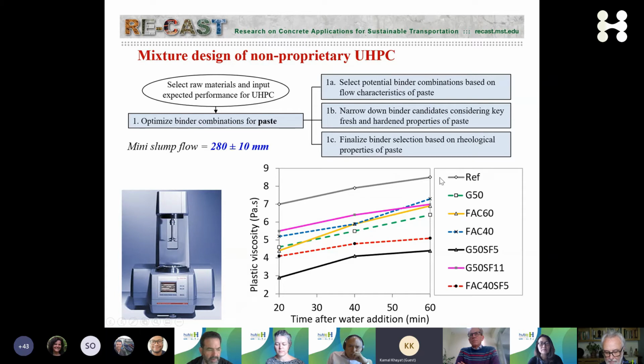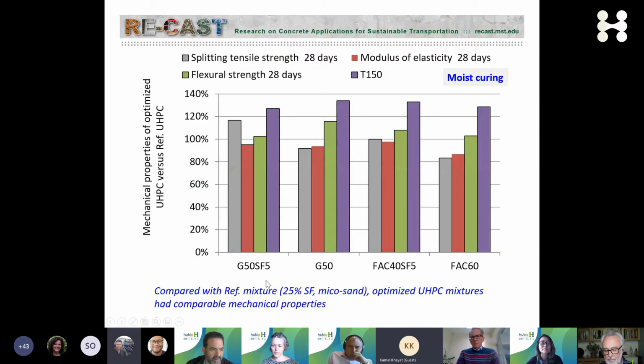We could see here some of the proprietary mixtures, like the one that was used in Sherbrooke, with 22 to 25% silica fume, is highly viscous. And by using different supplementary cementitious materials, fly ash, slag, silica fume, and combinations, we can reduce the viscosity. That means the material can be a lot easier to work with. We've also replaced some of the very fine sand, quartz sands, with regular concrete sand, working with packing density and what have you. And if you compare these mixtures, for example, this one is a GGBS slag cement, 50% and 5% silica fume. It gives you very similar mechanical properties as that of the proprietary mixture, which is 25% silica fume.